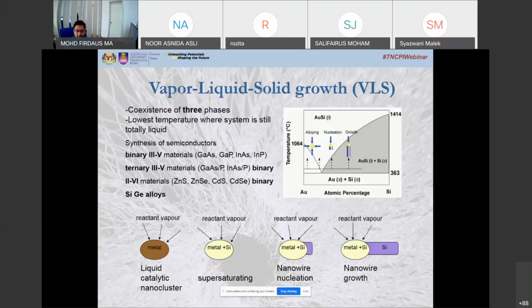And then the catalytic effect is responsible for the reduction of silicon at the gold droplet. So the gold-silicon droplet absorbs vapor phase silicon, resulting in a supersaturated state. Then silicon atoms precipitate from the supersaturated droplet because the melting point of silicon is higher, and this results in the growth of the silicon nanowires. So here, the one metal they are using is gold, and this will lead to the formation of the silicon wires.